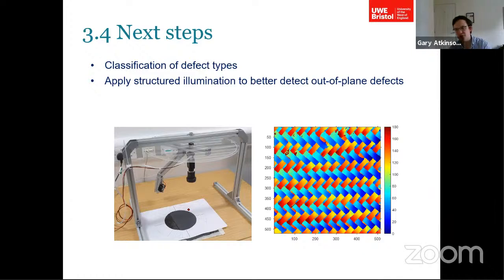So this is the sort of technology combined with polarization that will allow you possibly to detect a little bit beneath the surface, but it is very much relying on secondary effects. The truth is that computer vision is inherently a surface-based technology. There have only been a few attempts at subsurface inspection using standard computer vision. You really need infrared thermography or ultrasound to probe beneath the surface.